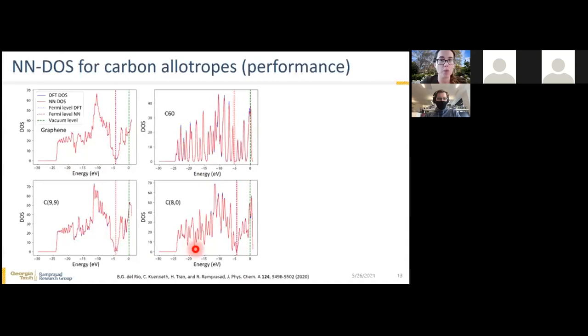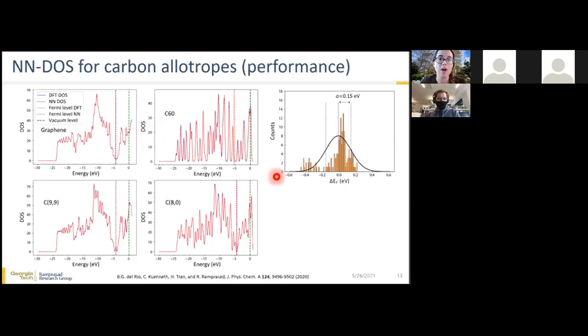And as an example here, I'm showing the performance on test configurations for graphene, C60, and 2 carbon nanotubes, C(9,9) and C(8,0), where the predicted DOS, here in red, follows very closely the reference DFT density of states, which is in blue. And likewise, the Fermi level computed from the cumulative integral of the predicted DOS, which here we show in dashed red line, coincides with the DFT Fermi level, which is shown in dashed blue line. Now, the histogram of the error in the calculated Fermi level from the predicted density of states follows a Gaussian distribution where the instances with a high error drastically decay after 0.2 eV.